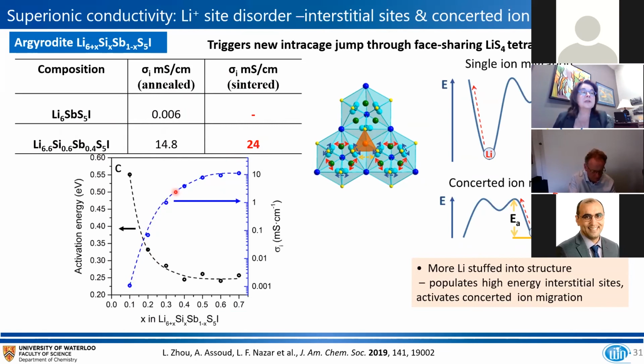And this conductivity is strictly a function of the lithium content. And the reason for that is that lithium populates a metastable interstitial site. And this forms a stepping stone for transport from one cluster to the next, literally. And that lowers the activation energy for the transport and triggers what we call concerted ion migration, because as one ion moves, it undergoes Coulombic repulsion with the ions in this site, and it literally pushes that ion to the next cluster. And so this is, I think, a very powerful strategy for increasing conductivity, this whole idea of stuffing lattices into metastable interstitial sites. And we're planning to expand on this in the years to come.